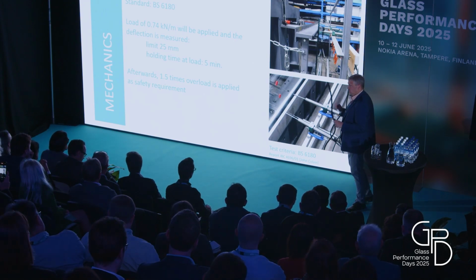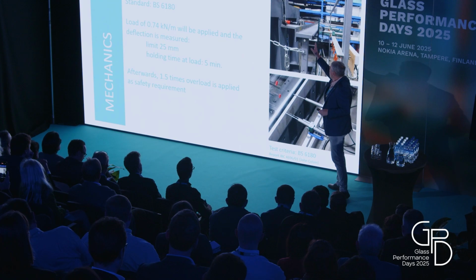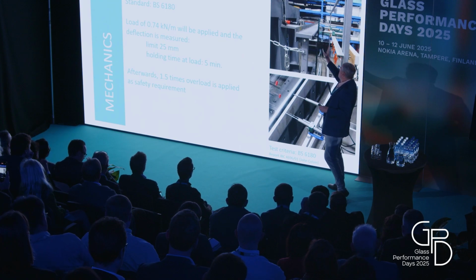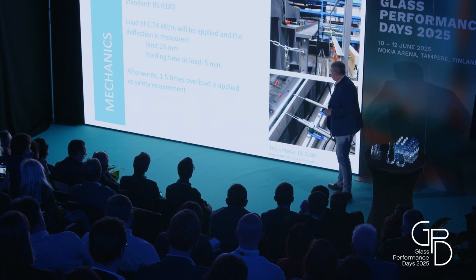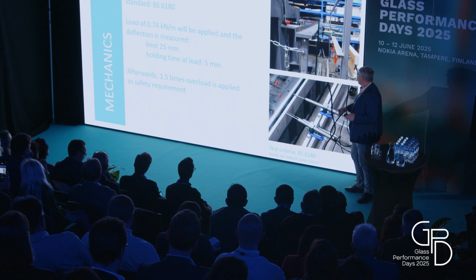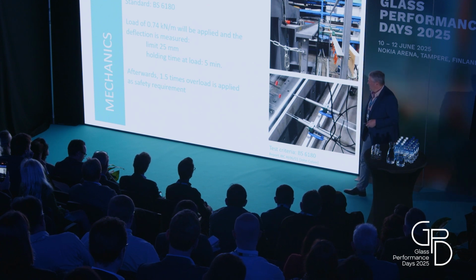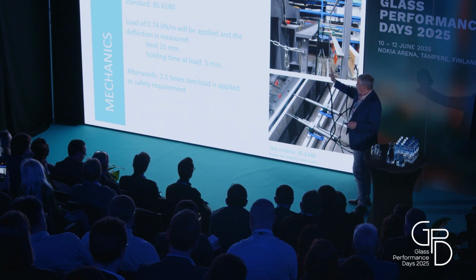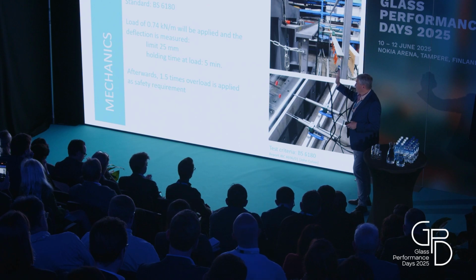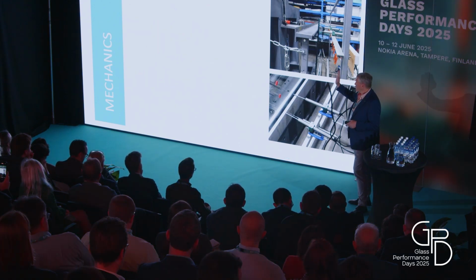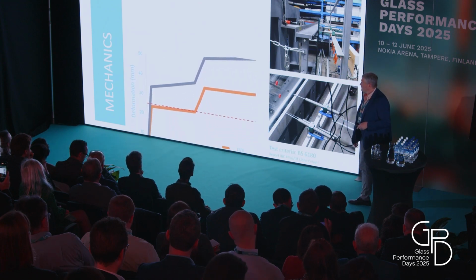the deflection. You apply the load, and the glass will deflect in this direction, and you can see here the sensors for measuring the deflection. Once you have applied the load, you wait for 5 minutes to check if there is a change in deflection, and then you increase it to the safety level of 1.5.